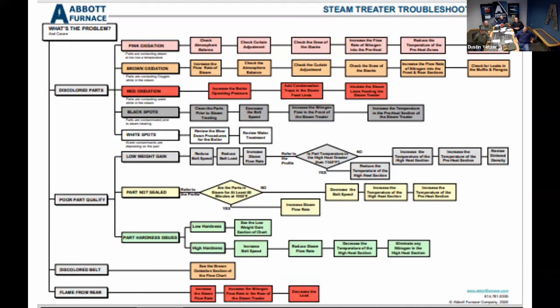The biggest and probably most popular is black spots or dark areas. And a lot of that relates back to contamination. So if you are doing some machining or some sort of dip on the part before it goes into the steam treater, the old adage, garbage in, garbage out. Sometimes there's an ability to remove some of that that the furnace can do, but for the most part, we want relatively clean parts going in so that we don't have those black spots on their way out.